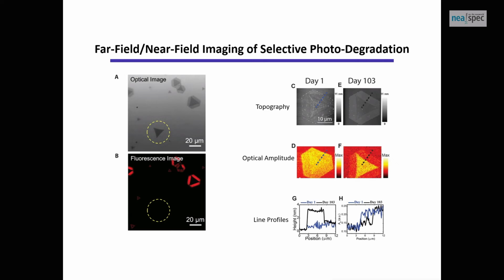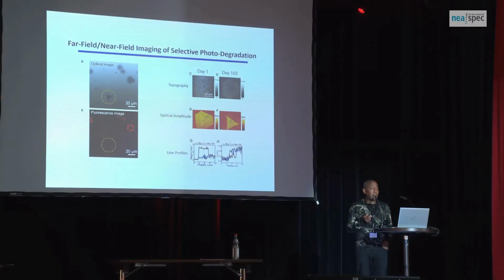So what you saw is photodegradation, clearly. If you look also with fluorescence imaging, which you could do with the same setup, you notice that for WS2 the outer layer is completely quenched, whereas the flakes that are not exposed to light are still glowing. So you can clearly say that the reason for the degradation is photo-induced. This is important. The other thing is, because you have this correlative imaging, you can now look at the topography as well as the optical image with second harmonic near-field image using visible light. We use 632 nanometer. What you notice is something very interesting.